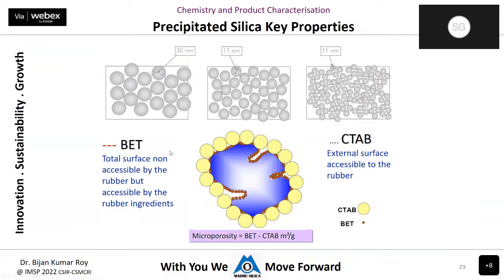The key property is the surface area. We have 2 types of surface area. One is the BET nitrogen surface area, and the other is the CTAB surface area. BET nitrogen, being a smaller molecule, can penetrate inside the pores, so it gives a higher surface area altogether. But the CTAB molecule is cetyl trimethyl ammonium bromide. It is a bigger molecule, so it cannot penetrate into the pores. So only the external surface area can be measured with CTAB. Since rubber is a bigger molecule polymer, the CTAB surface area is a major parameter that can be characterized in addition to the BET surface area.